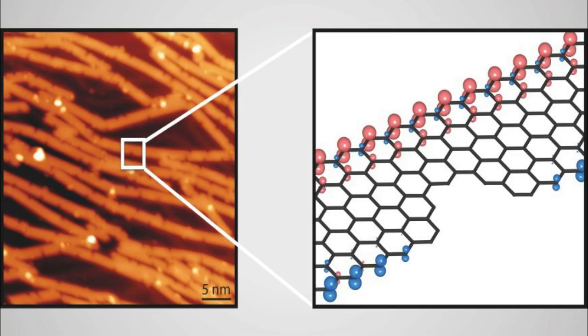A comparison between ZGNRs and AGNRs of equal width shows that transport across the former is less sensitive to the introduction of both single and multiple defects than in the latter. Overall, the research provides a global picture of the impact of these ubiquitous bite defects on the low-energy electronic structure of bottom-up graphene nanoribbons. Future research might focus on the investigation of other types of point defects experimentally observed at the edges of such nanoribbons.